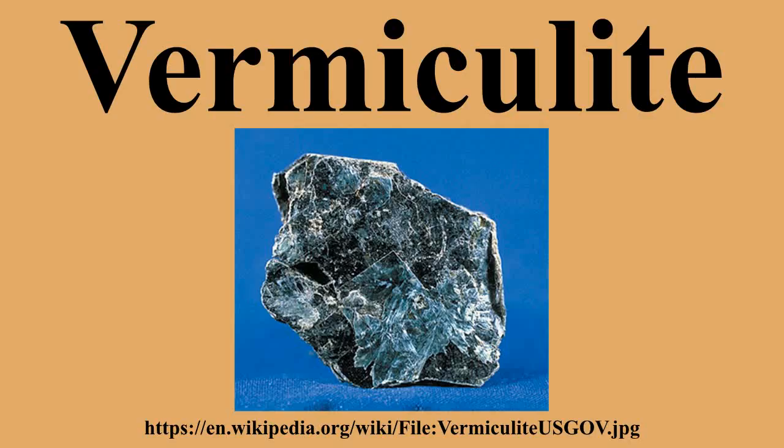Such parts can withstand service temperatures of up to 1150 degrees Celsius and are often used in the aluminium smelting industry as backup insulation behind the carbon cathode in the potshells which contain the molten mixture of cryolite and alumina.